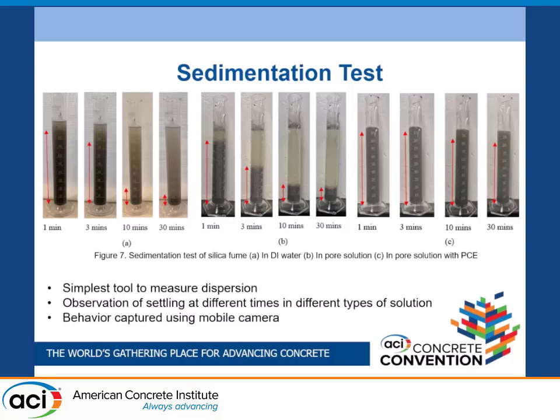And when we add PCE to the solution, we see that the solution is stabilized and the sample height has raised. So we can say this is one of the tools that tells us that in the pore solution, the particles tend to agglomerate.